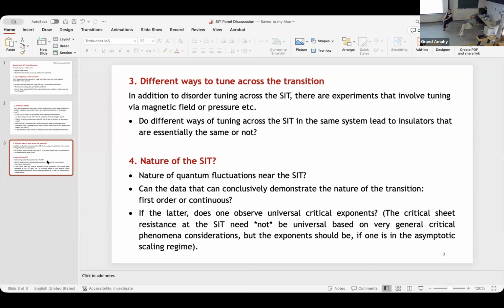That if you underdope thin films of cuprates, or in the case of Bonn and Hardy, single crystals of cuprates, then the superfluid density goes to 0. The TC also goes to 0. And both groups see very beautiful quantum critical scaling, which we can discuss. And this is a bit strange because when you underdope and destroy superconductivity completely, you're presumably going into some insulating state with weird magnetism. And just as you said, it's very unusual for two states with two different broken symmetries to come together at a critical point.